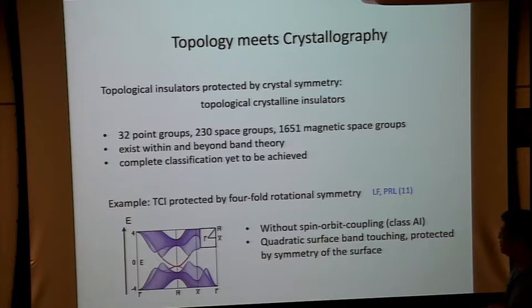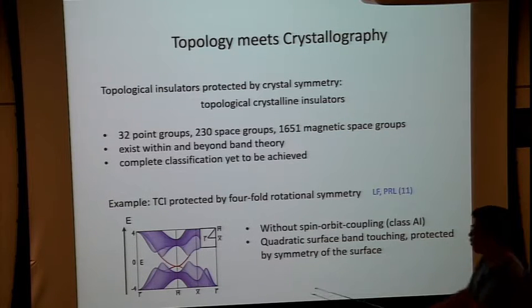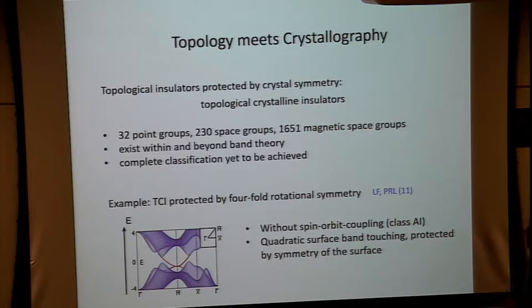An early example of such phases is a topological crystalline insulator. This is within band theory and is protected by the fourfold rotational symmetry in the tetragonal crystal. You can think of it as stacks of square lattice, so there's a rotation symmetry along the z-axis. In this particular example, this kind of topological phase does not require a spin-orbit interaction. Within the tenfold classification scheme, this is within class AI. As you can see, the surface of this topological crystalline insulator has quadratic surface bands that touch each other at a high symmetry point, and this band crossing is protected by the fourfold rotation symmetry.